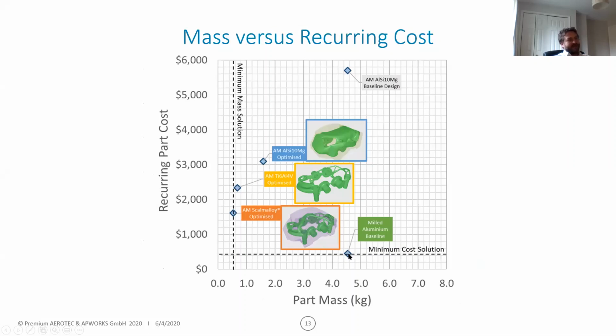Unfortunately, we didn't do that exercise. Maybe it's one to do, but you would have a line going in this direction. With the additive solution, it's the other way around. So you have your baseline design just printed by additive is far, far more expensive. If we had a maximum cost solution boundary, that would be it. But what we see is with optimization and then optimizing material as well, we actually see that with AM, we're on a different direction of optimization. When we save mass, we save cost.